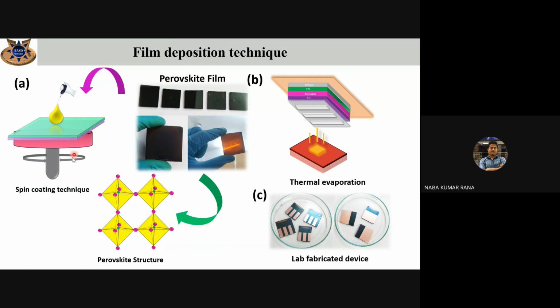And this is the spin coating technique we are using here in our lab for the deposition of the perovskite thin film. And this is our perovskite film, and this is the thermal evaporation technique.